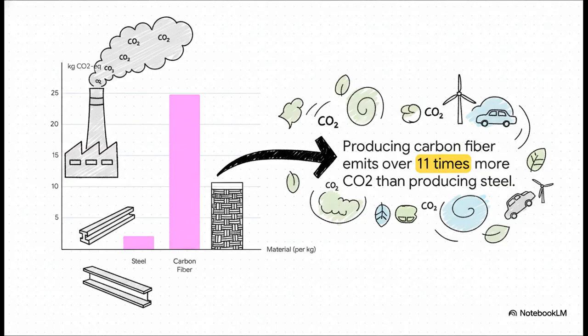And where there's that much energy, there are emissions. This chart just lays it out so clearly. Making 1 kilogram of steel, which is not exactly a green process itself, pumps out about 2.1 kilograms of CO2. Now look at carbon fiber, almost 25 kilograms. That's not a little more, that's over 11 times higher. It's not even in the same ballpark.